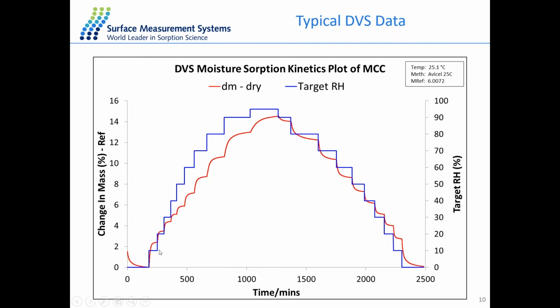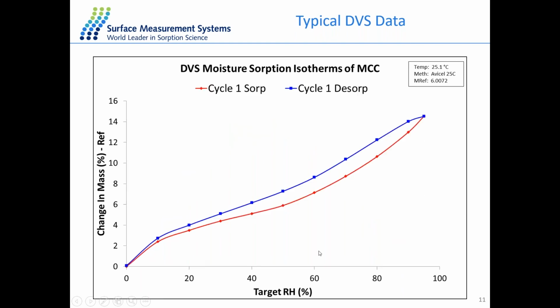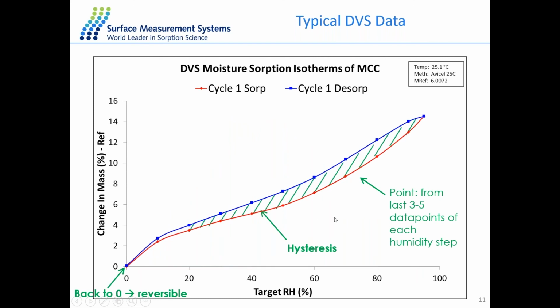For the isotherm, we take the equilibrium mass change at each humidity and plot it against the target relative humidity. Then we can get this isotherm with both sorption and desorption. So this isotherm will tell us lots of different information. For example, at 90% RH, the total water capacity of this sample is about 14%, so the sample has very good affinity with water. And this water is not just sitting on the surface by surface sorption, but it also goes into the bulk of the material. That's why there is a formation of the hysteresis gap between the sorption and desorption isotherm.